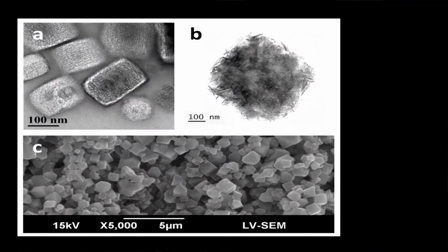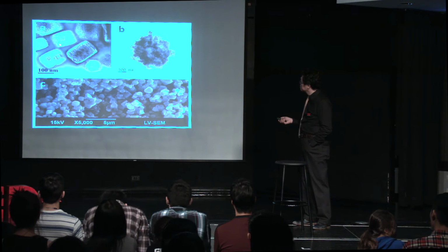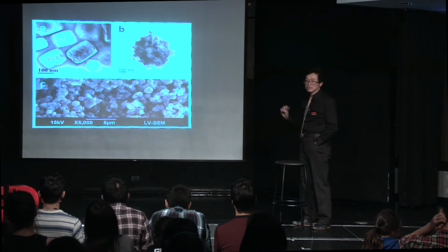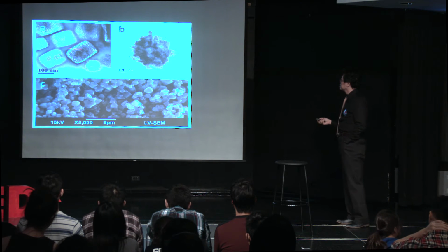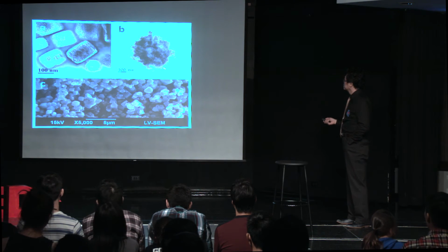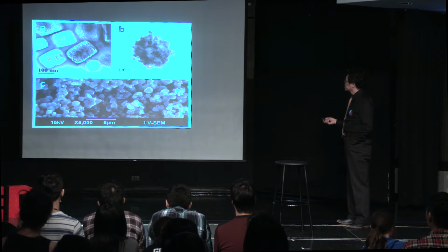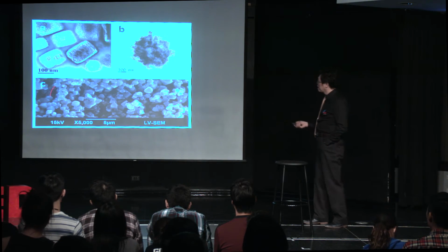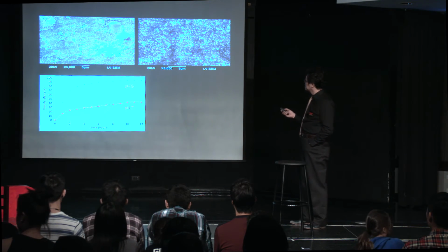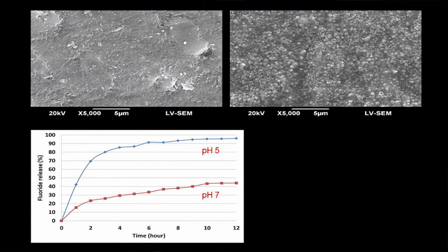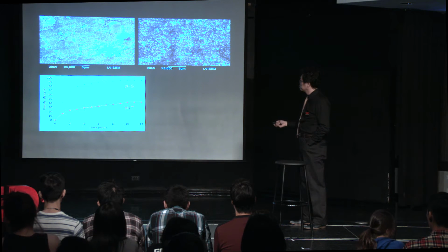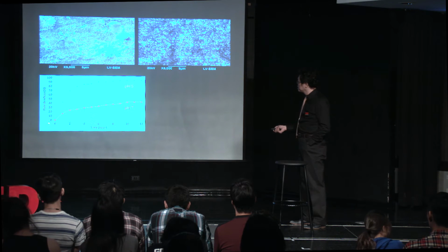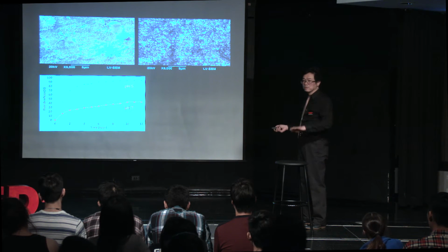Well, this is a particle. See, this is 100 nanometers in size. If you look carefully, you see the cross-stitched, and this is the polymer surface. And then you assemble the attachment fingers on top of it, so make it like this. And you can make tons of these. And because under very acidic pH, the ingredient is released abruptly, while in the neutral pH, it is released constantly and gradually.